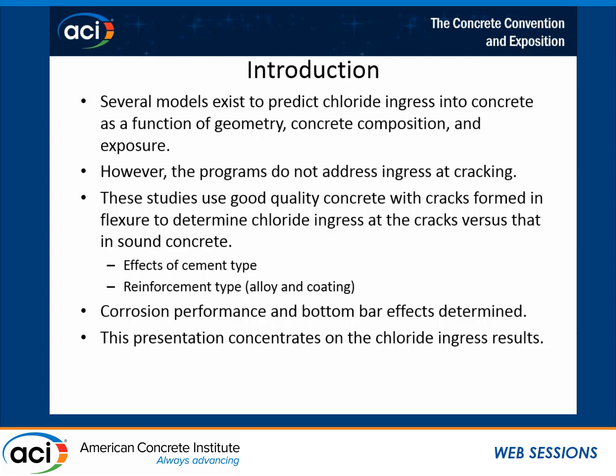You'll see we have a sample that's 6 inches high. We've got 2 bars on the bottom and a bar on the top. The crack, even though it doesn't go all the way down to the bottom bar, actually will have an effect on chloride at the bottom level. So it's not only the top level of the steel reinforcement you might have to be worried about, you also might have to worry about the bottom levels. Corrosion performance was determined at both of those, but I'm not going to concentrate on the corrosion aspects. I can answer questions on it later on because given 20 minutes, you can't do everything.